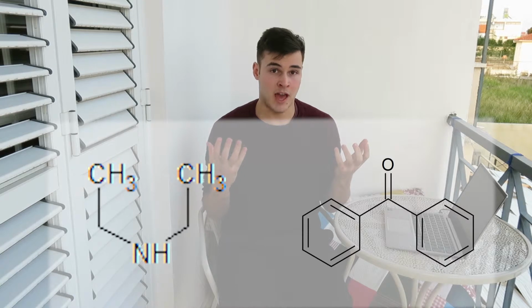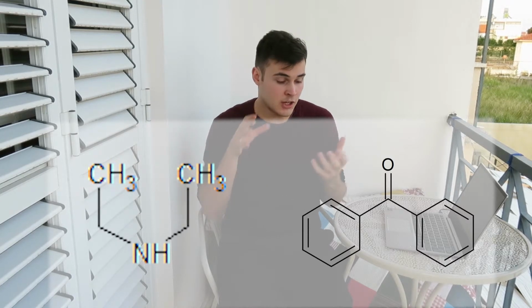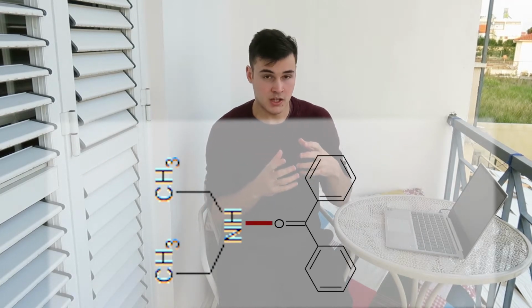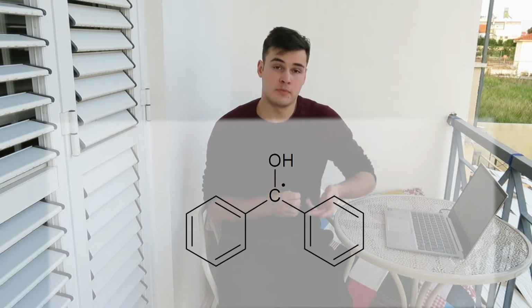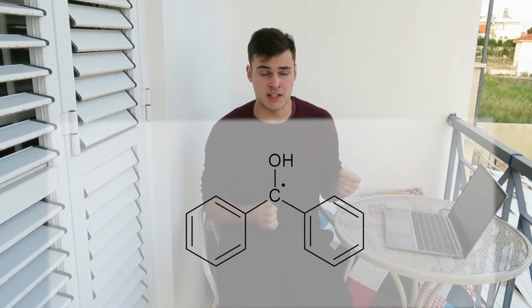In type 2 photoinitiators, the primary initiator requires the aid of a secondary compound to help it form its radicals. As an example, here are benzophenone and diethylamine to aid it. Through a hydrogen donating complex, they form this hydroxy-substituted radical, which is much more active. The trade-off between the two types is that of a high K radical value against the much better optical absorption of type 2 initiators. Hence, they require less intense UV light.